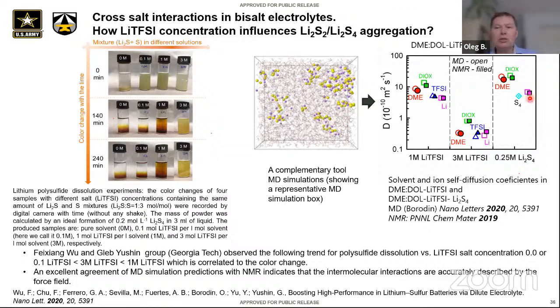What I also did, I said, okay, now I'm going to just make Li2S4 aggregate much more. And when I aggregate it that much more, it changes lithium diffusion; it drops dramatically. So that to me is indirect evidence that with non-reactive force fields, there are non-interchangeable species. Just want to be clear here. So that's a downside, but we are taking this Li2S4. I think it's a reasonable description of how aggregated species are and how solvated they are.